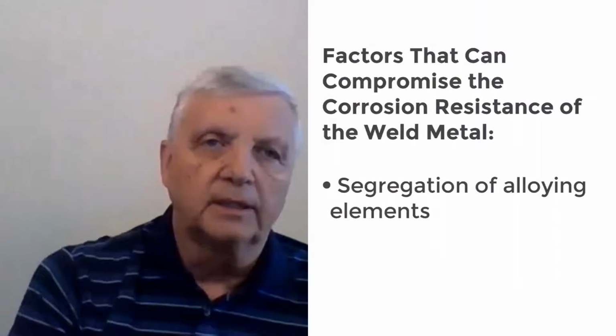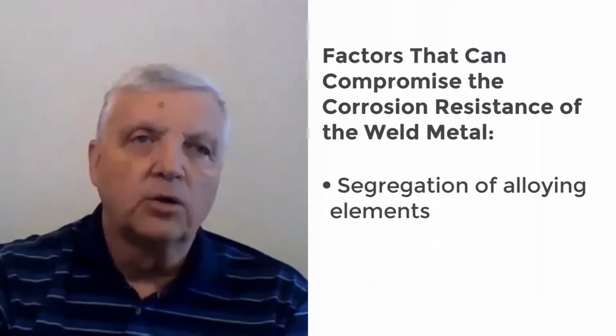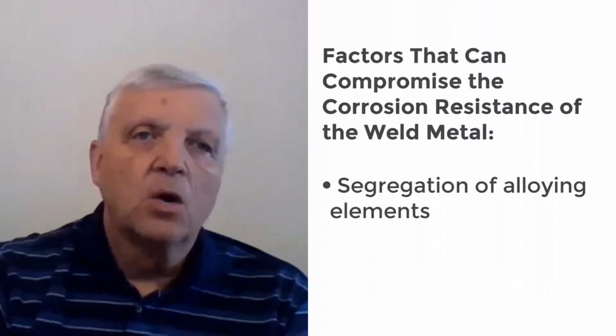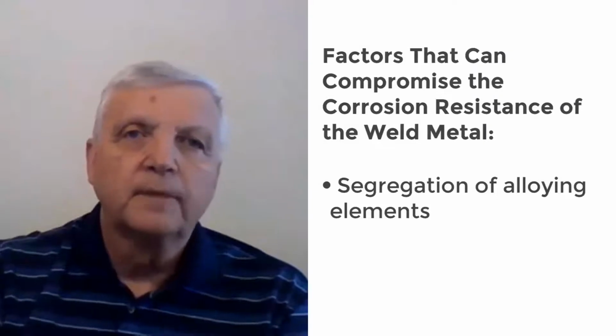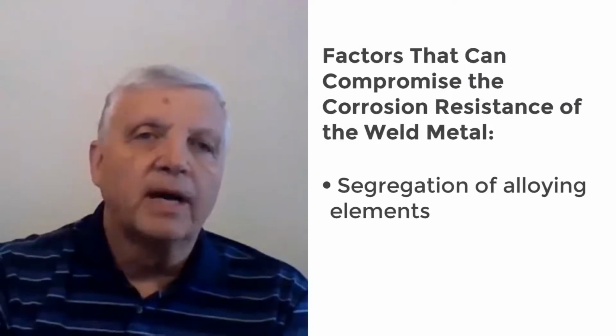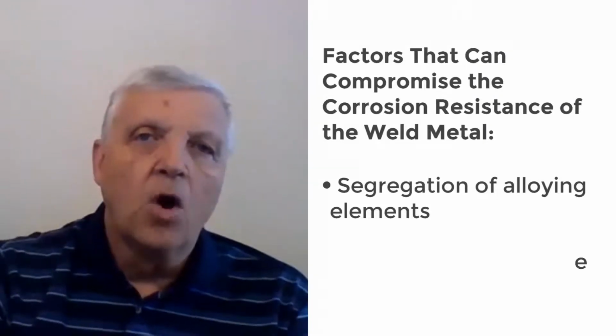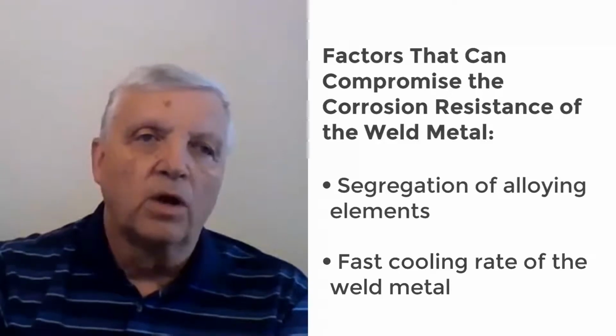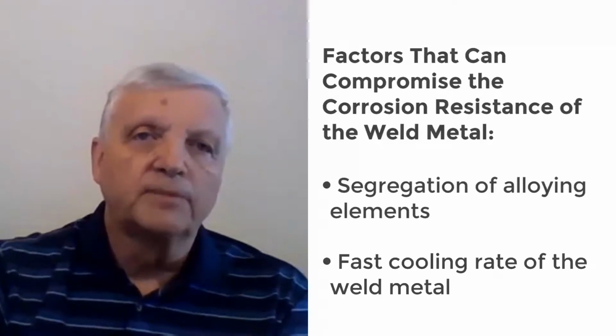Also, solidification of the weld metal will result in segregation of alloying elements present in the weld metal. This segregation of alloying elements becomes more pronounced with stainless steels of higher alloying, which can potentially compromise the corrosion resistance of the weld metal, or the fast cooling rate of the weld metal will prevent the formation of an optimal microstructure.